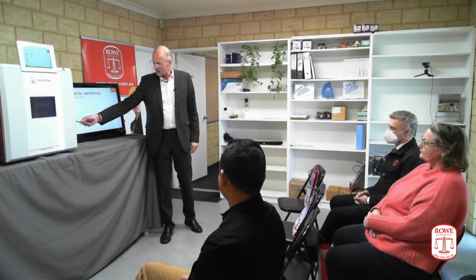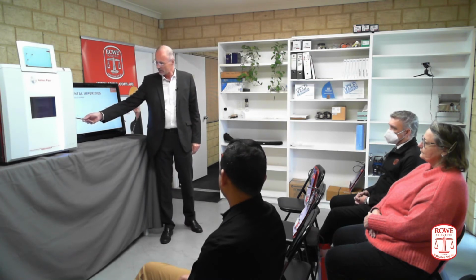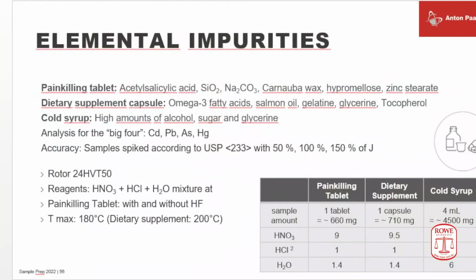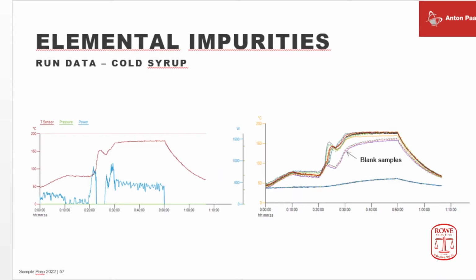Again, we have a look at the temperature profiles, programmed in a two-step way. First, a short heating ramp and a heating plateau below 100 degrees for the initial reactions to take place, and then heating up to 180 and holding it for another 30 minutes. What you can see here from the course of the reaction, the red curve to the right, is a temperature peak. And we already know this comes from exothermic reactions inside the vessels. So the instrument recognizes that it's a very severe, very spontaneous reaction going on, but it can cope with it. You won't face any problem from that.